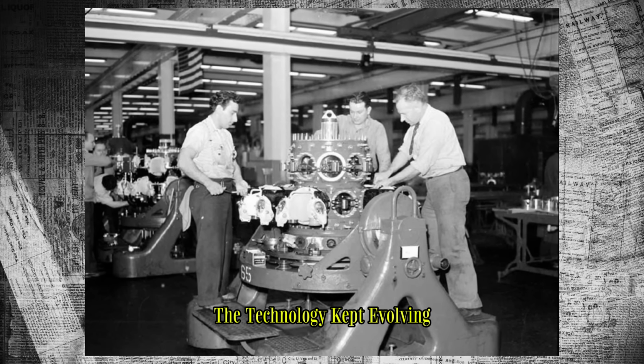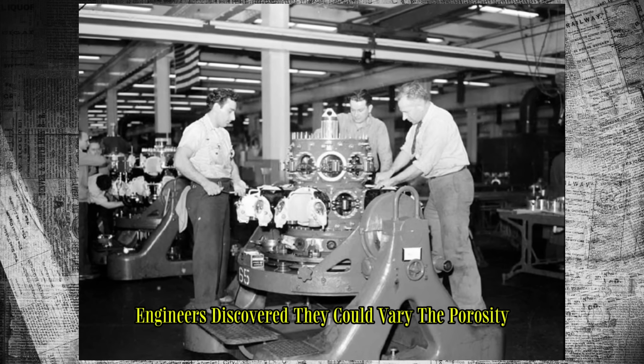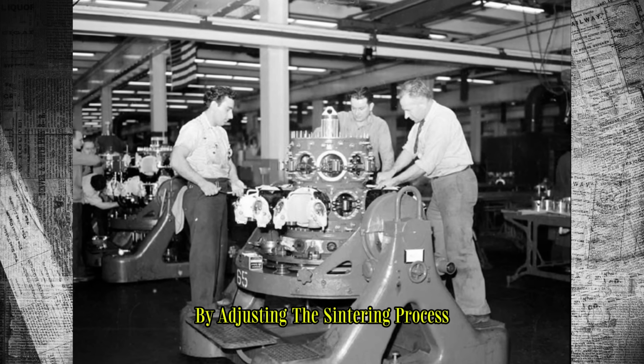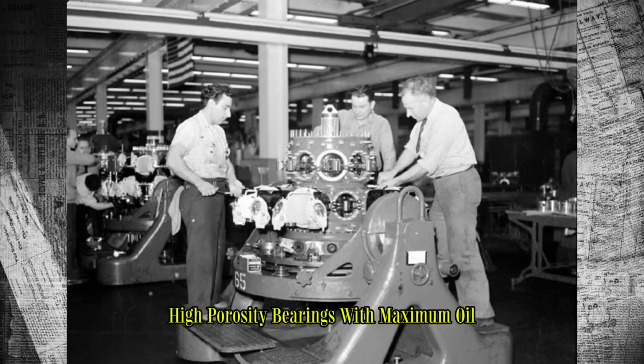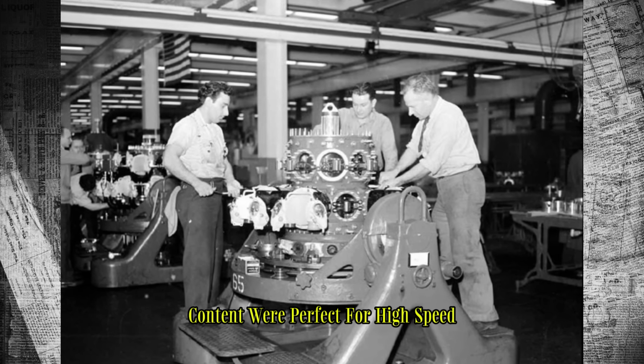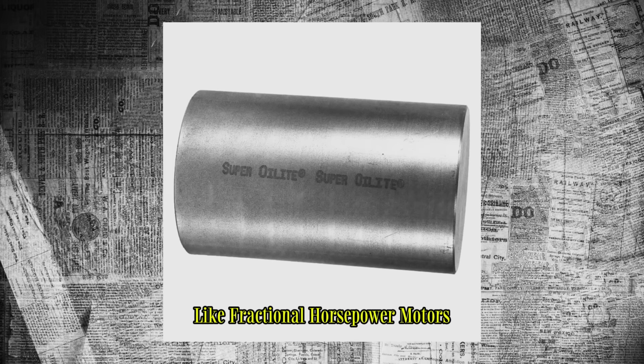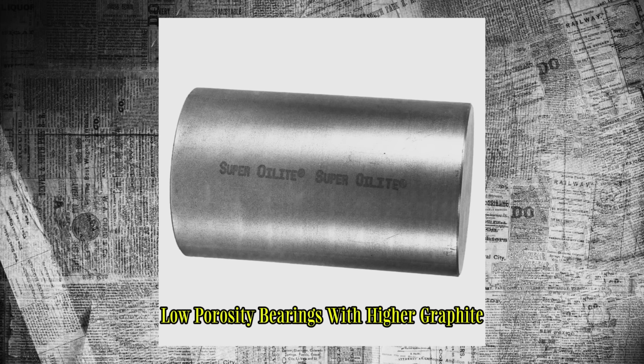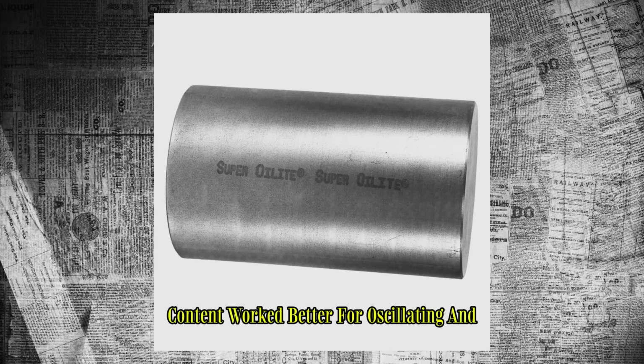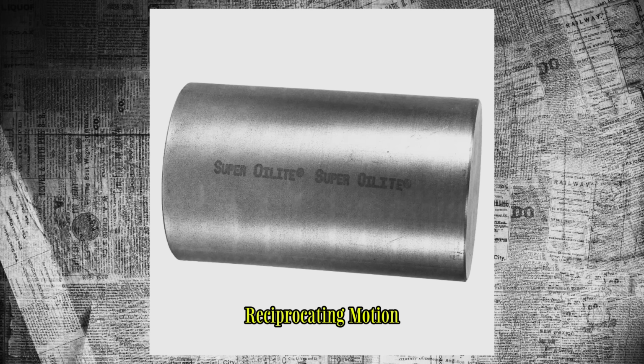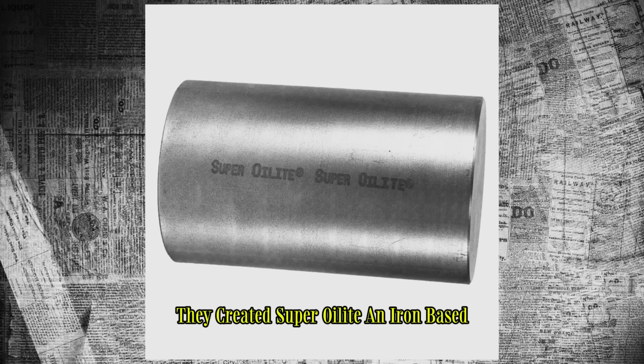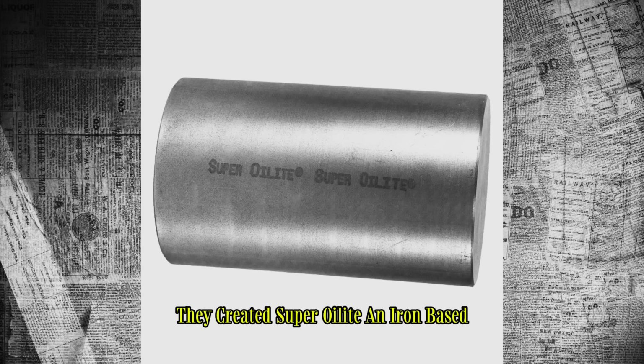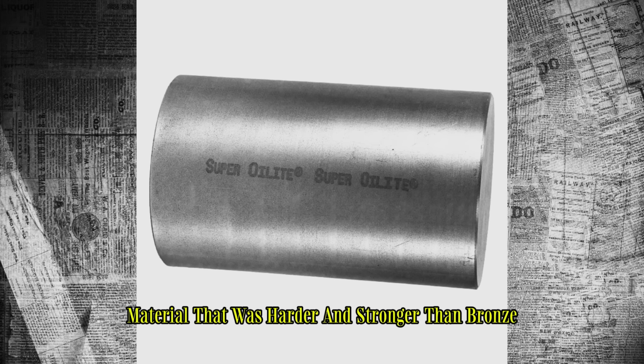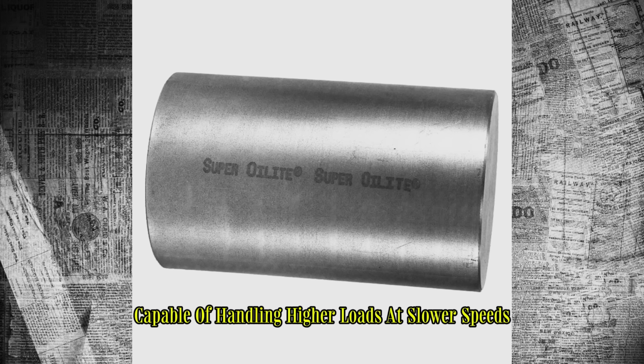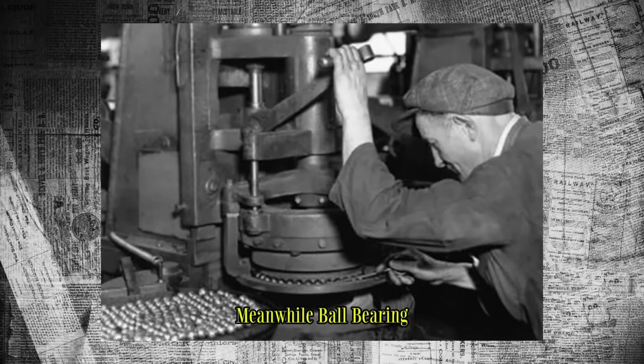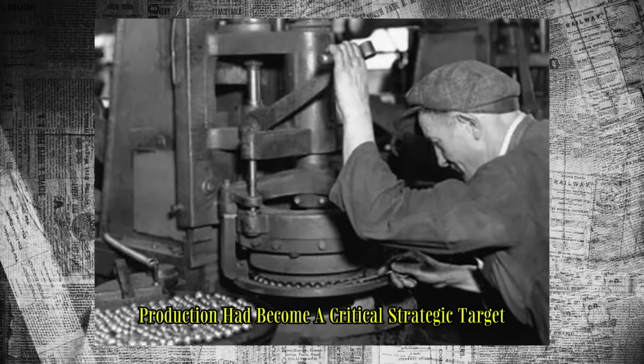The technology kept evolving. Engineers discovered they could vary the porosity by adjusting the sintering process. High-porosity bearings with maximum oil content were perfect for high-speed light-load applications like fractional horsepower motors. Low-porosity bearings with higher graphite content worked better for oscillating and reciprocating motion, where building an oil film was difficult. They created Super Oilite, an iron-based material that was harder and stronger than bronze, capable of handling higher loads at slower speeds.